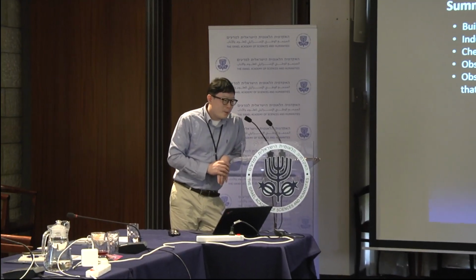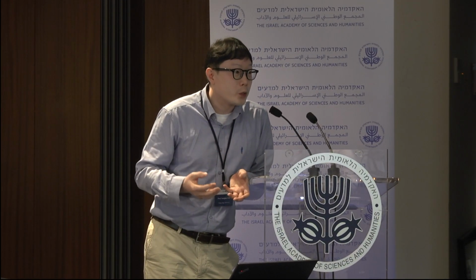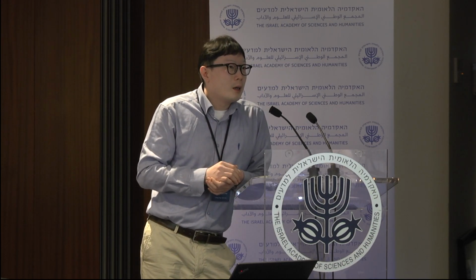Yes. This is just our observation and our measurements. It is hard to tell what is really the origin of these results. But I'm going to divide it into two parts. The first part is the magnetic chain on a lead substrate, very similar to niobium, but we do see a Yu-Shiba-Rusinov region of states within the gap. So it looks like the 1D magnetic chain is magnetic, but not strong enough to fully suppress the superconductivity. It partially breaks the Cooper pairs nearby, but it will not completely break the superconductivity. So that was the first part.